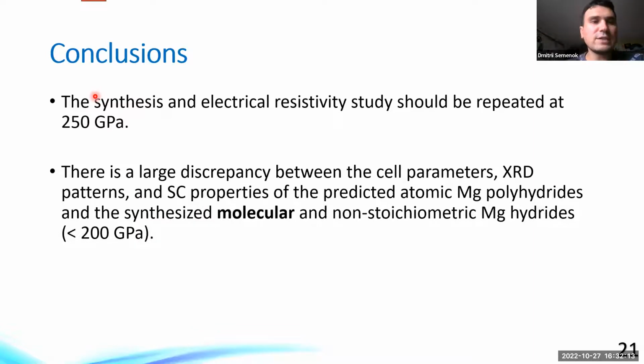I would like to point out again that there is a large discrepancy between the cell parameters, X-ray diffraction patterns, and superconducting properties of the predicted atomic magnesium polyhydrides. In many papers, I showed you that it was predicted that even magnesium H3 should demonstrate a TC over 100 kelvins. But in fact, we do not see anything like that, and the synthesized polyhydrides are probably molecular and non-stoichiometric.